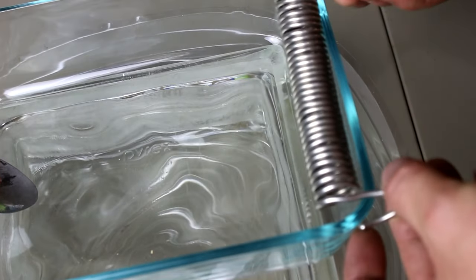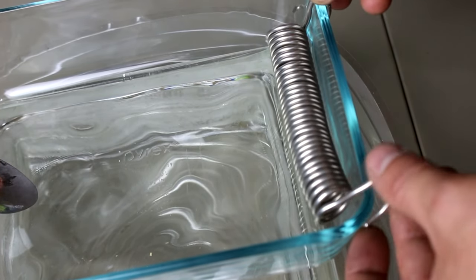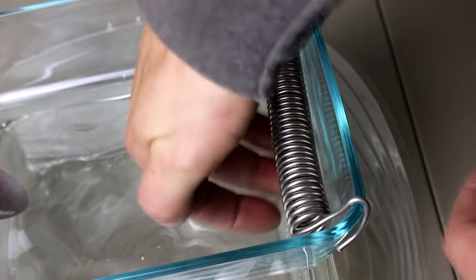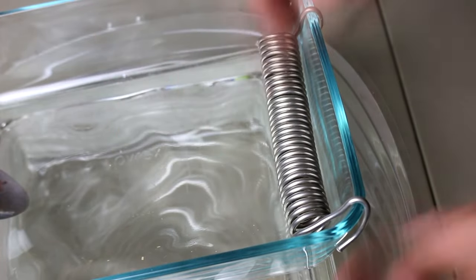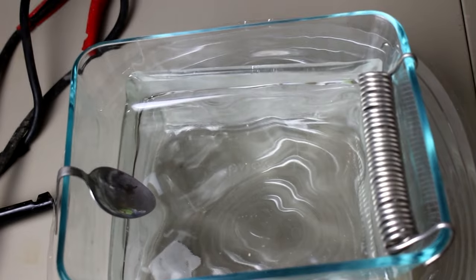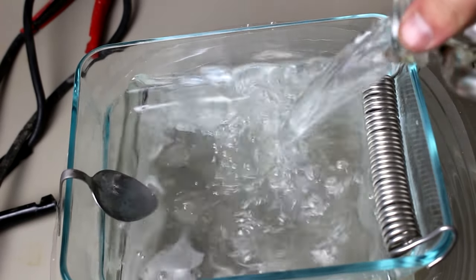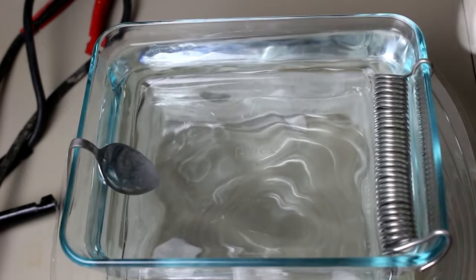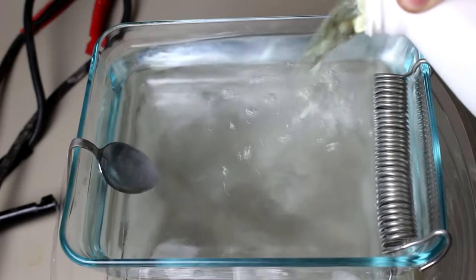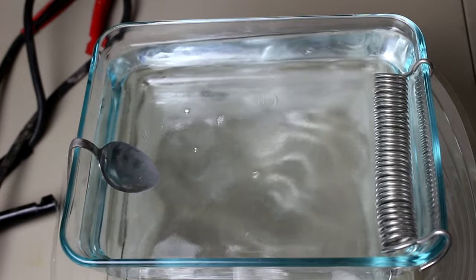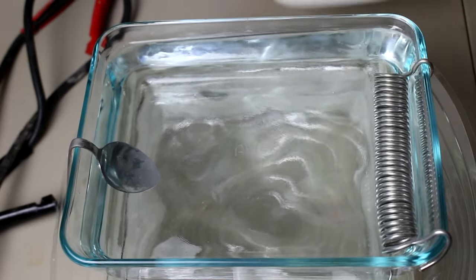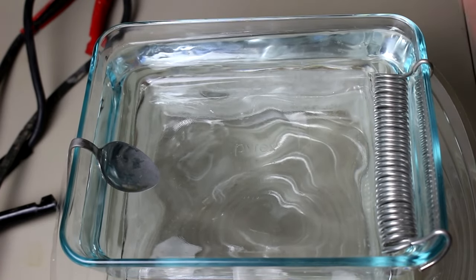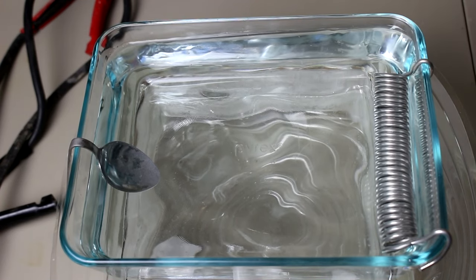So this is what I've come up with here. I've just wrapped this into a coil around a piece of a half-inch dowel, and I've bent the ends so I can hang it on the edge of this glass dish. A little bit of space underneath so materials can fall off of this and not short things out. So now for the electrolyte, which is primarily going to be water. I'm going to add enough water to completely cover the coil here. I'm just going to add a splash of muriatic acid. Now this is mostly just because it conducts electricity really well and has lots of chlorine. If there's chlorine in the solution, the silver will not be soluble. I suppose you could use salt, but if you've got muriatic acid, you may as well because it'll actually react with the tin a little bit.